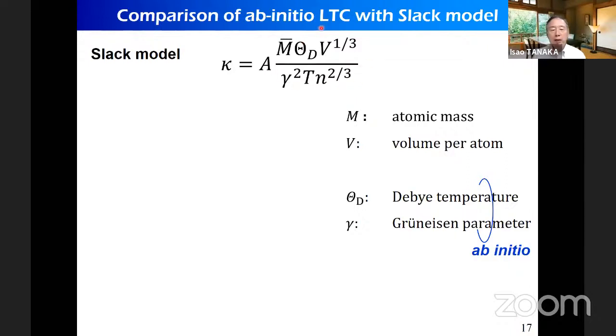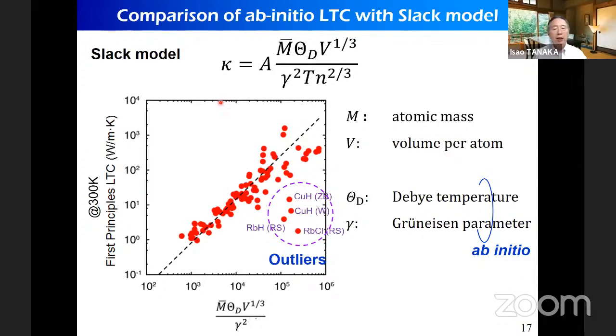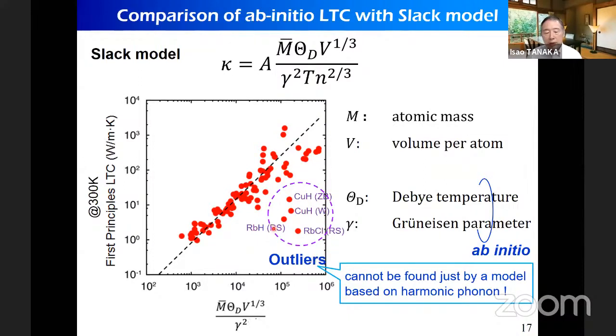So let me compare this quantity with the theoretically computed lattice thermal conductivity. You can find many of the data points are on this diagonal line. It means this Slack model is quite a good model. But at the same time, you can realize there are some outliers. We know the reason for these outliers. These outliers are located here because this Slack model was obtained based on the harmonic phonon model.